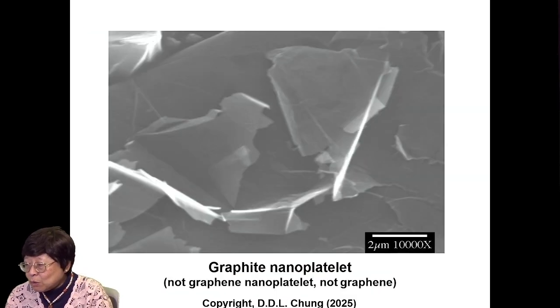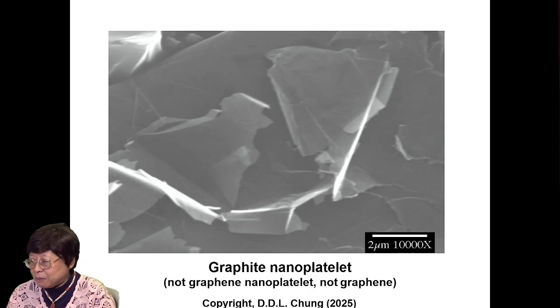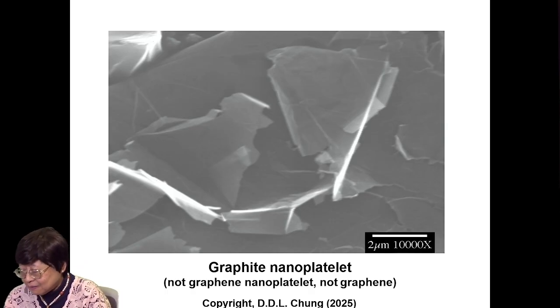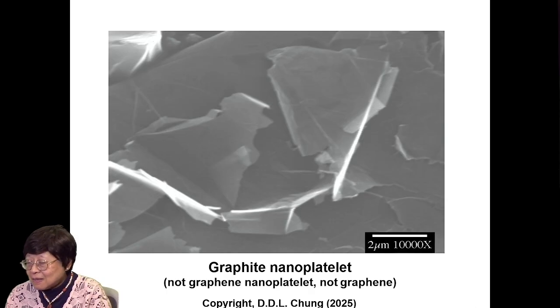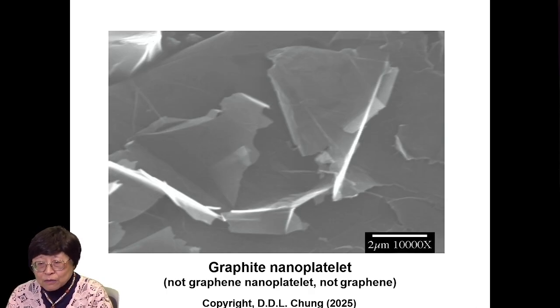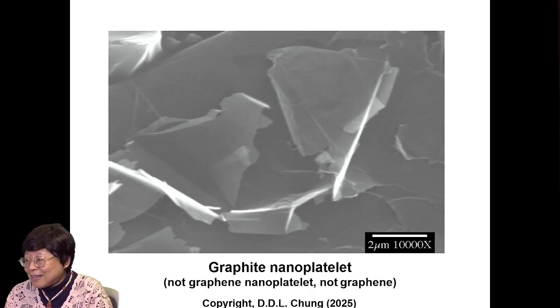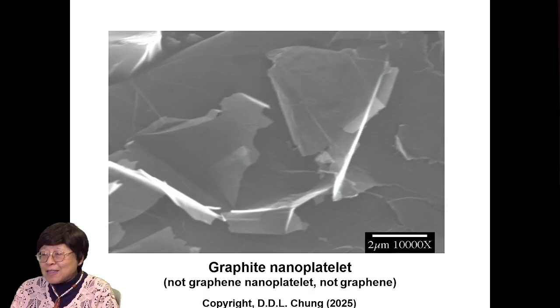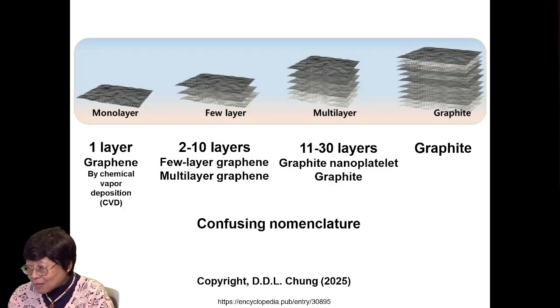This is graphite nanoplatelet. It shows pretty thin platelets. But this is not graphene nanoplatelet. It's not graphene, okay? Because the thickness is not below that of 10 layers of carbon. Very often, the thickness is not even known. So one cannot say that it's graphene if you don't know the thickness.